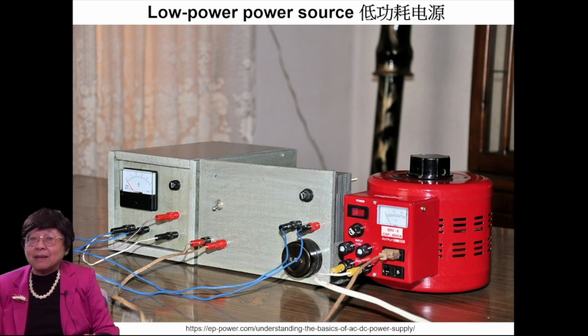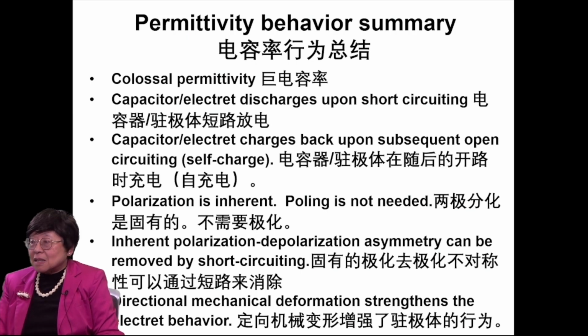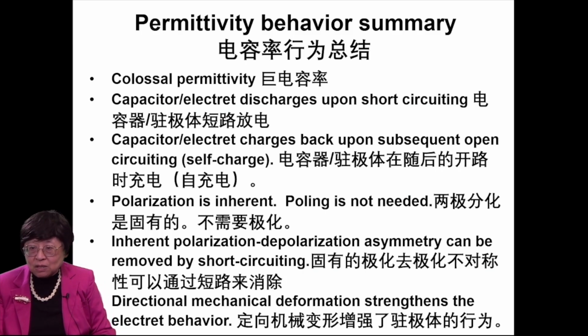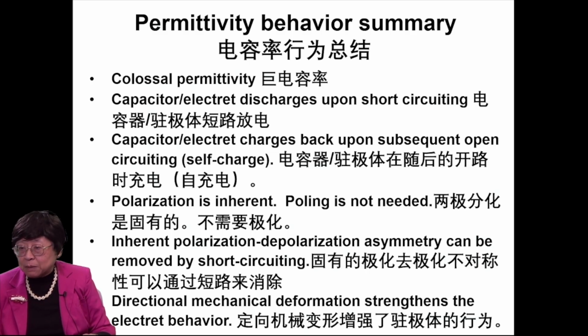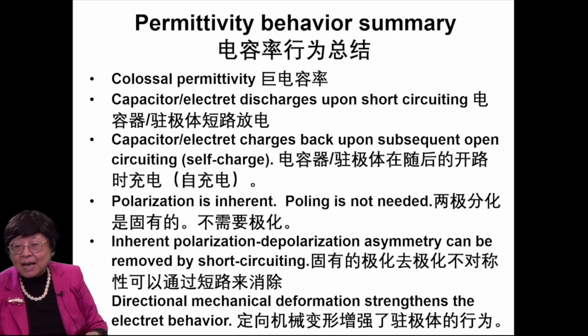The power provided by the electrodes is very, very small. We're talking about low voltage and low current, but low power source has its industrial need. So this is a summary of the permittivity behavior. Colossal permittivity. The capacitor or electret discharge upon short circuiting, and it charges back upon subsequent open circuiting. That's self-charge. Polarization is inherent. Poling is not needed. Inherent polarization, depolarization, asymmetry can be removed by short circuiting. Directional mechanical deformation strengthens the electret behavior.